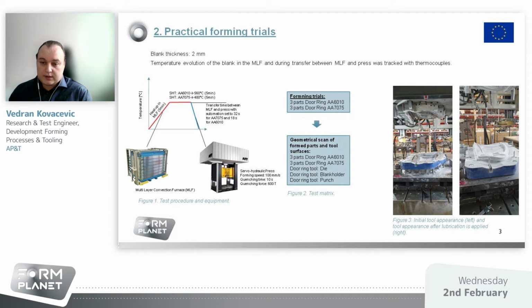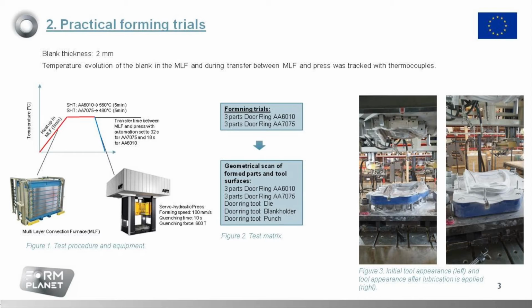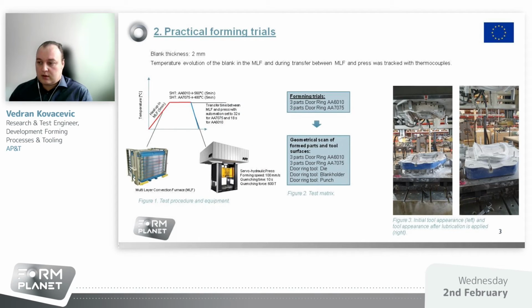The practical forming trials were executed in AP&T's aluminum test line. The test line is equipped with a multi-layer convection furnace and a 600-ton servo-hydraulic press. To execute the trials, we used a scaled car door ring to form parts with a sheet thickness of 2 millimeters. The following test procedure was implemented. First, the blanks were heated in the MLF to a solutionizing temperature of 560 degrees for AA6010 and 480 degrees for AA7075. The blank was then transferred from the MLF to the tool in the press, where it was formed at an average speed of 100 millimeters per second, followed by quenching at 600 tons for 10 seconds. We formed 3 parts from each alloy, respectively.